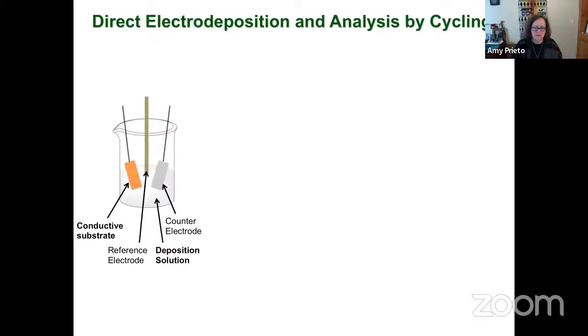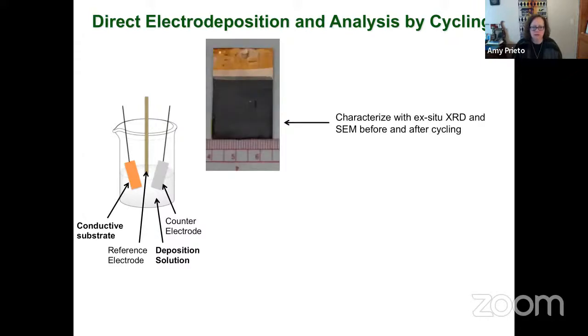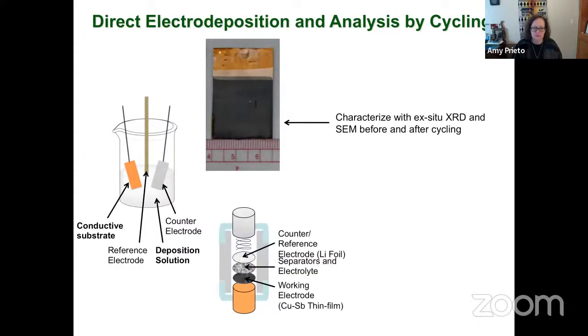So in general, in my group, when we're trying to use anodes and trying to study how they behave, we follow this workflow. We use normal electrochemical cells. We plate onto large flags. This is the image I'm showing you on the top. That can be characterized with X-ray diffraction, scanning electron microscopy, energy dispersive spectroscopy, and we can look at these before and after cycling. We punch discs out and assemble them into Swagelok cells that we can take apart. So we can do sort of post-mortem analysis of how these materials fail.